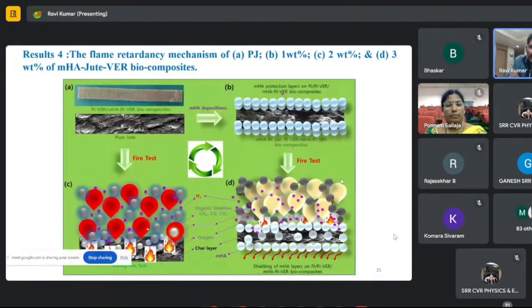So this image shows the mechanism of the burning property of any panel. You can see the pure jute, and after making the PJVER, MHA PJVER biocomposite, when we catch the fire, it does not allow oxygen to pass to the surface. It arrests the surface by preventing the oxygen molecules from penetrating. These spherical spots, or spherical images, show the nanoparticles which arrest the oxygen so it does not penetrate and feed the fire.